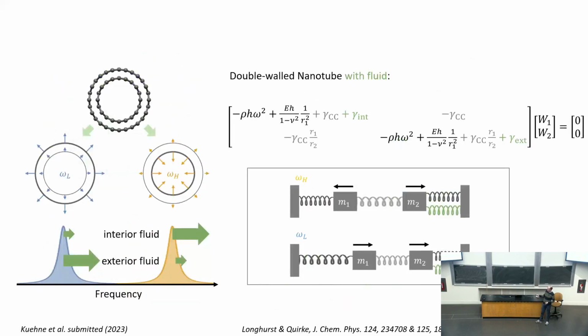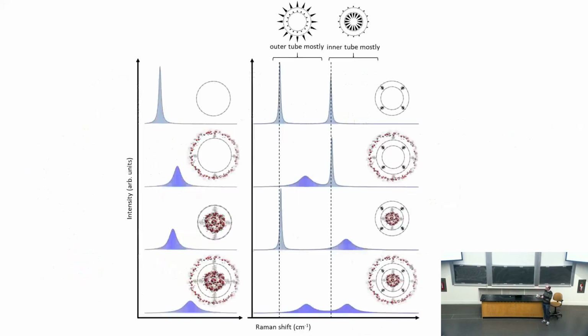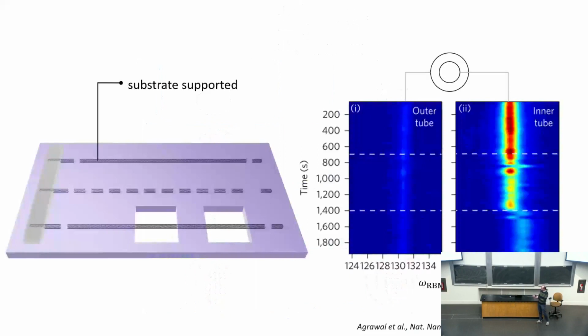We also suggest that what's nice is if you take a double wall nanotube, you can separate the effect of coupling on the inside and the outside, because when you have two walls, they couple like a classical coupled oscillator. You get two frequencies, and one corresponds more to the displacement of the inner wall, the other to the outer wall, and you can decouple the effects of where fluids are. So it's a very nice tool to specifically sense a fluid at a specific position. And here are studies we've been doing. Actually, this was before my time, but here's a double wall nanotube.